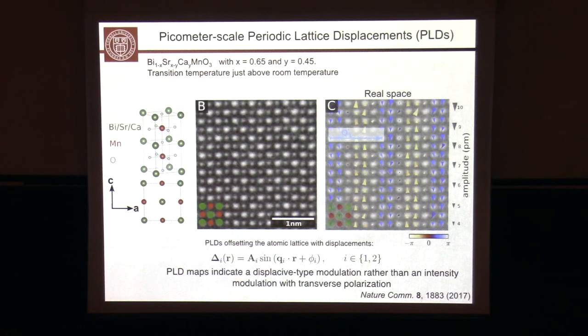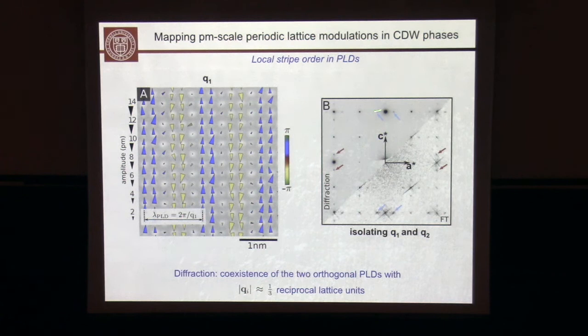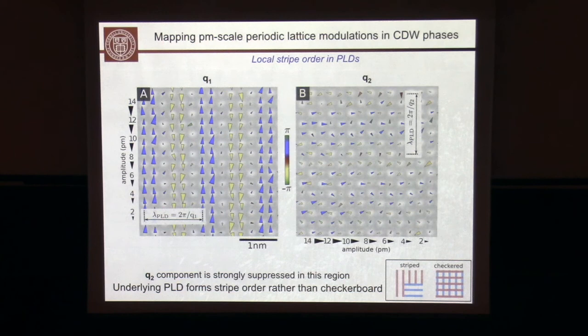and we want to extract that quantitatively. Okay, so now remember, I showed you two sets of peaks, two orthogonal sets of peaks. The question is, if you go to the local scale, do we still see both order parameters? And so this is the picture you have for Q1. That's the order parameter in the direction to the right. But when you extract the modulation in Q2, which is orthogonal, it's strongly suppressed. So the picture that arises is that of local stripe order compared to this overlapping checkerboard pattern.